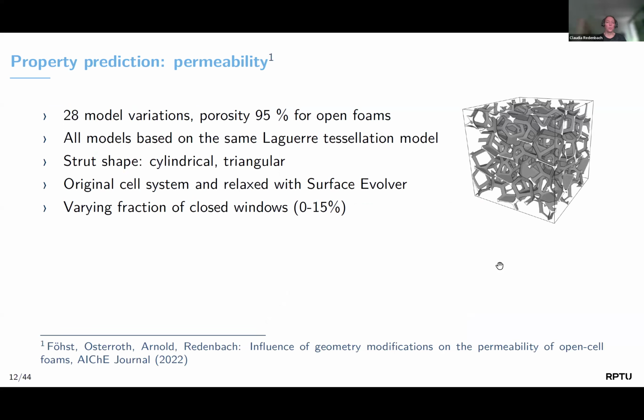And well, when deciding which kind of model to actually use for printing, you would also have to ask how the filtration properties are related to the microstructure geometry. And this we investigated in a simulation study, at the moment only focusing on permeability. So in the first place, there are no particles or cells present. We are just interested in the flow of a liquid through the material. So we looked at various model variations. We fixed the porosity to 95%. I mean, porosity would clearly have a very high influence on permeability. This we didn't want to study, but rather basically everything else. So we fixed also the same Laguerre tessellation. So kind of the frame of this filter medium would always be the same.